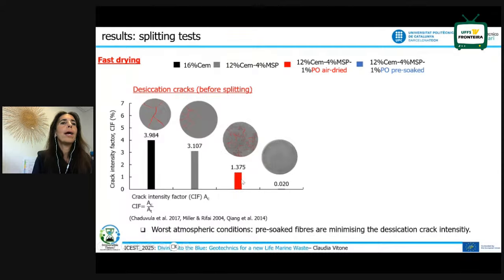When we perform fast drying, before splitting, we could observe desiccation cracks. These are images of the specimens after the 4 days of fast drying. You can see that essentially these desiccation cracks are very huge for the control mixtures, but if we add the fibers, in particular the pre-soaked one, we do not even see the cracking anymore.